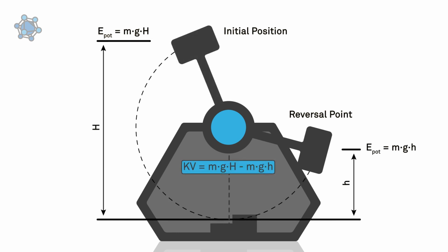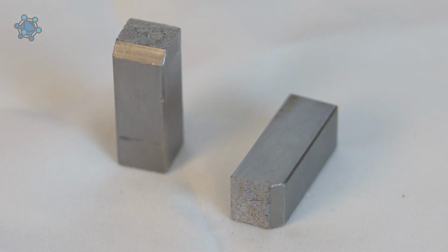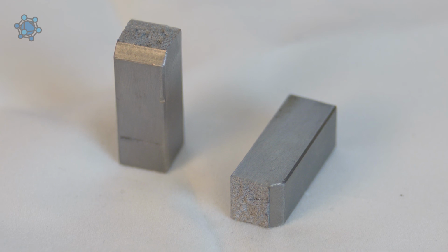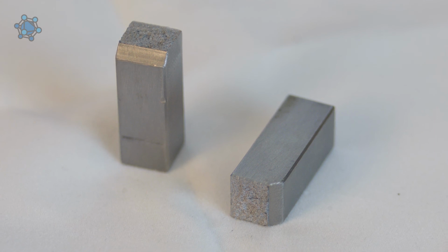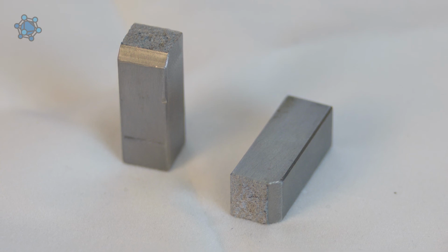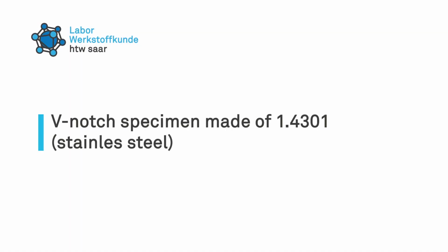The difference between the initial and the final potential energies is the energy that was passed onto the specimen in the form of the Charpy impact energy. The first specimen shows almost no signs of plastic deformation. You can see that the fracture surface is almost flat, slightly glittering even. Both qualities are strong indicators of brittleness, so now we know that this material can only absorb a small amount of impact energy.